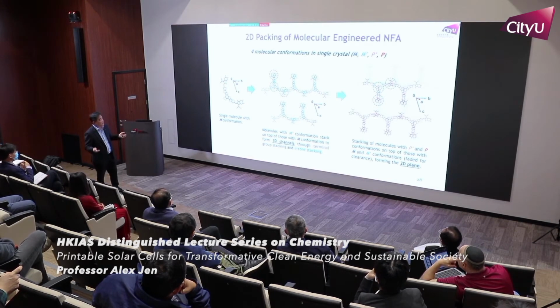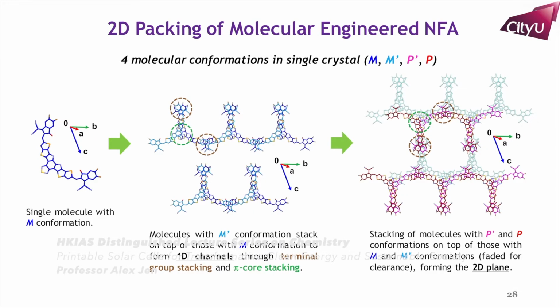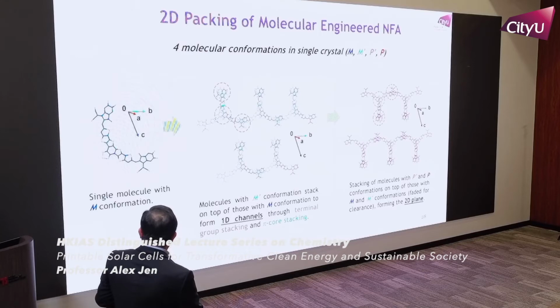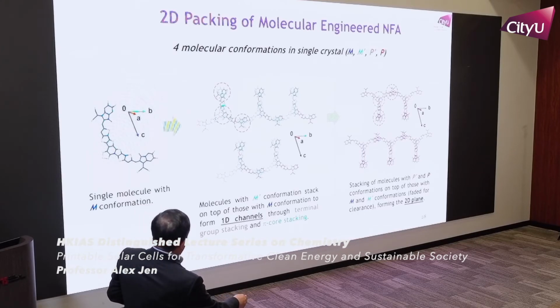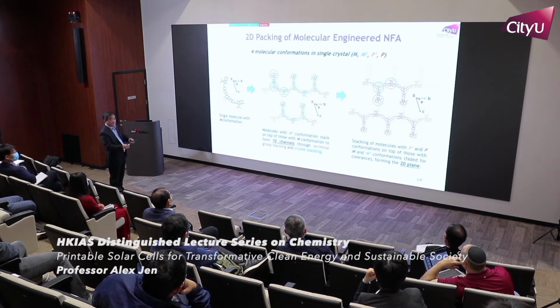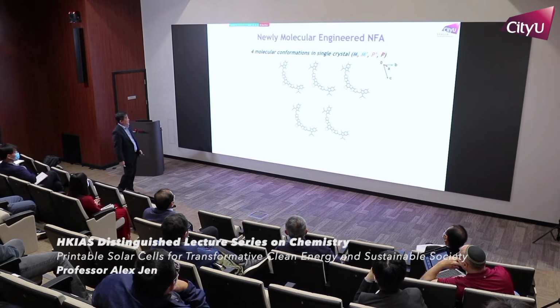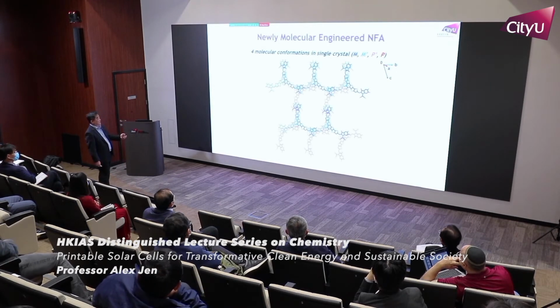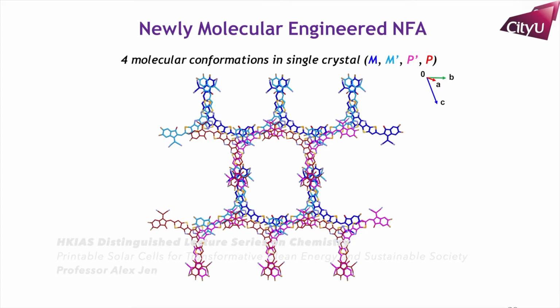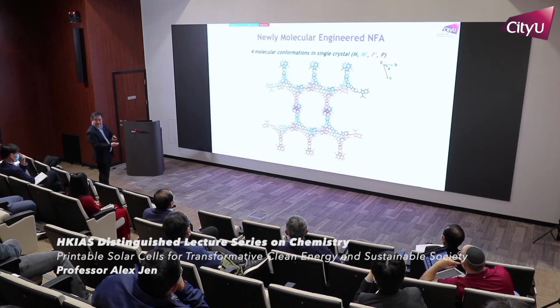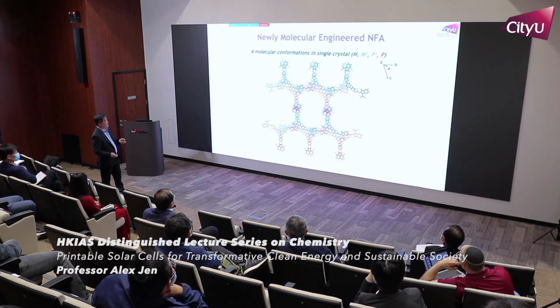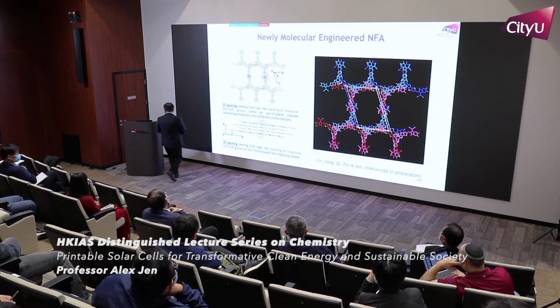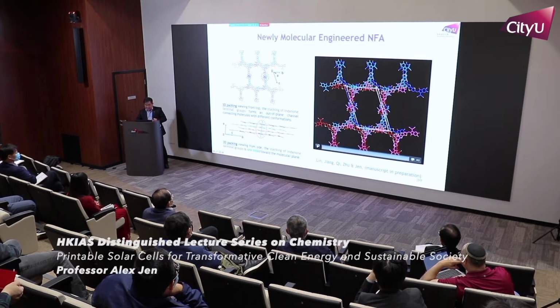But for the molecular engineer, the non-fullerene acceptor, you can see that this acceptor has four conformer isomers, right? The first one is where you have one unit, and M overlaps with M prime, so you form a linear chain. So instead of a single molecule, now you connect into a linear line. But when another two isomers come in, they start to stack on top of each other. This one becomes a 2D type of arrangement. So you can see that this is a new one in our new design. Then they form very ordered packing, with all the acceptors stacking right on top of each other. So this will help you to really transport your charges. So if you look at this, it is a very beautiful single crystal, also generated from that.